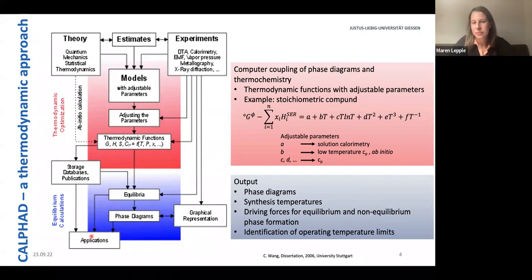So the output are, of course, phase diagrams, but one also can calculate, for example, or derive synthesis temperatures, or identify the operating temperature limits. One can calculate driving forces for equilibrium and non-equilibrium phase formation, or, if one is interested in batteries or electrochemistry, one could calculate the open circuit voltage for the electrochemical reaction, for example.